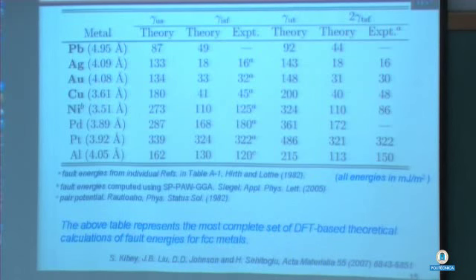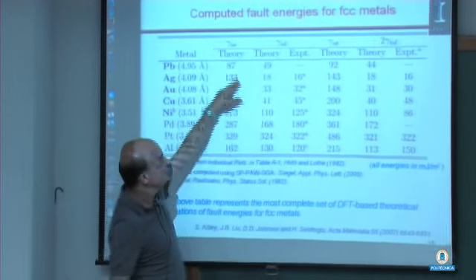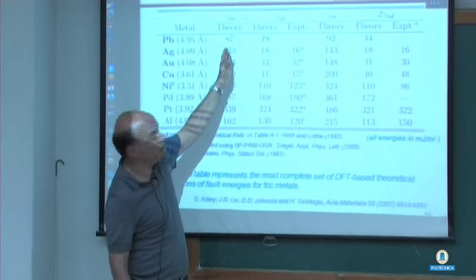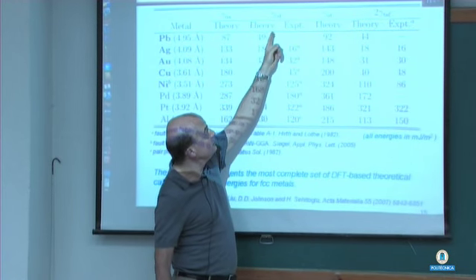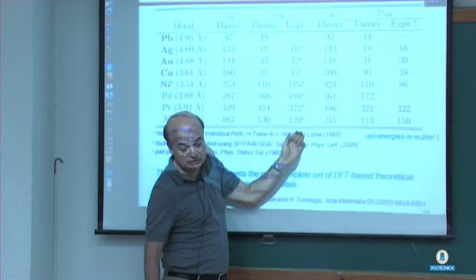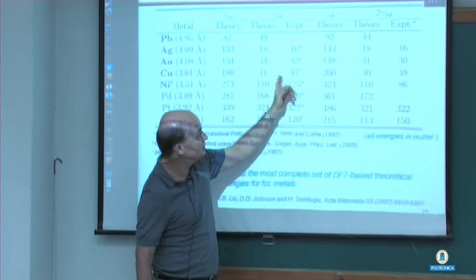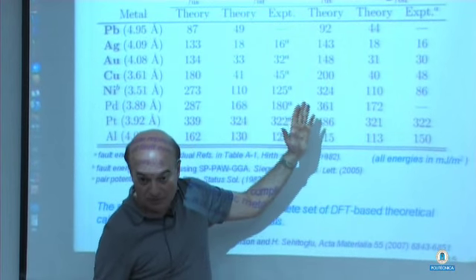Now, if you look at the results that we have, I plot here lead, silver, gold, copper, nickel, palladium, platinum, aluminum, right? These are the theoretical results for the energies. These are the experimental results. You cannot get an experiment for the unstable value of the energy, okay? But for the intrinsic stacking fault, you can get the energies experimentally, and they are in excellent agreement with our calculations. For gamma UT, we have the theoretical results. You can't get experimental results. And then for 2 gamma TSF, there's also good agreement.